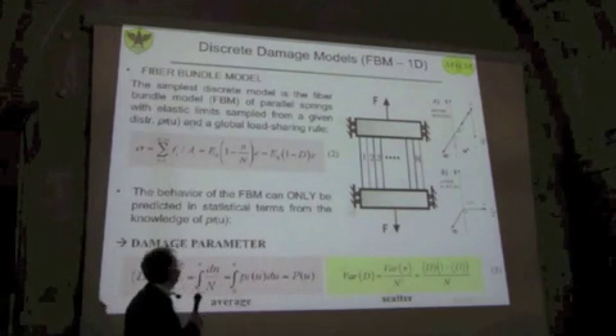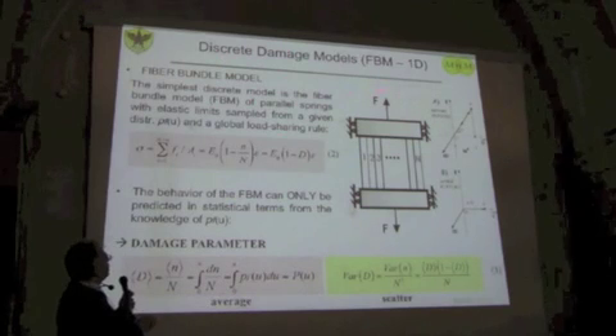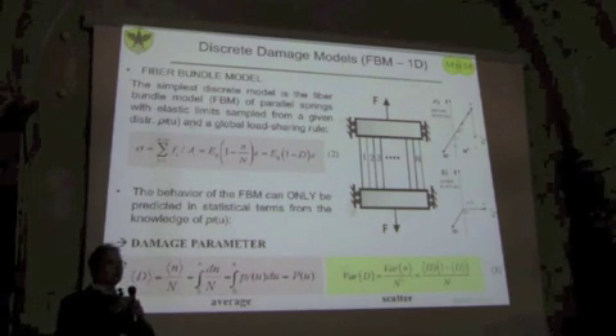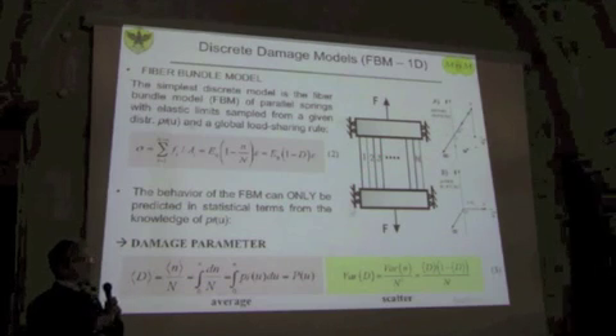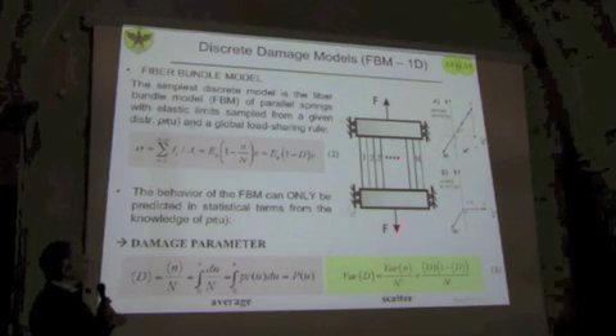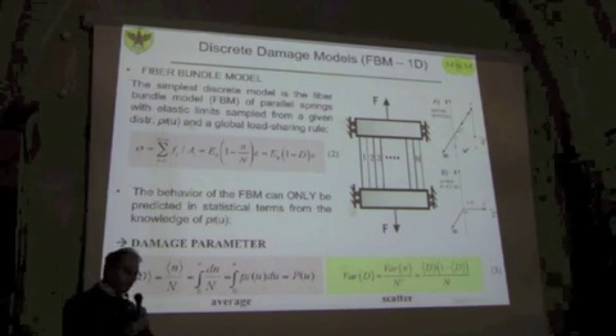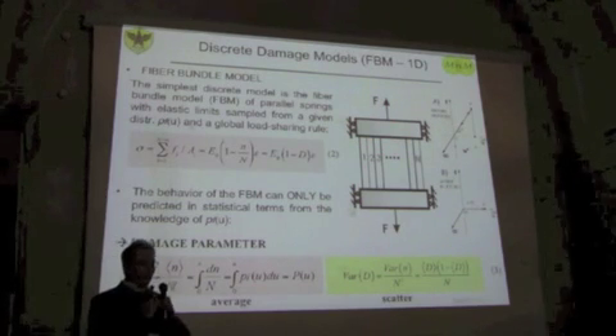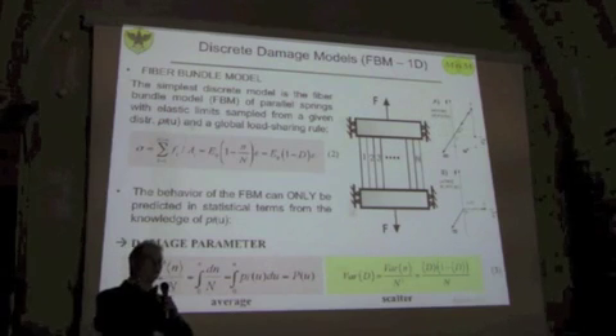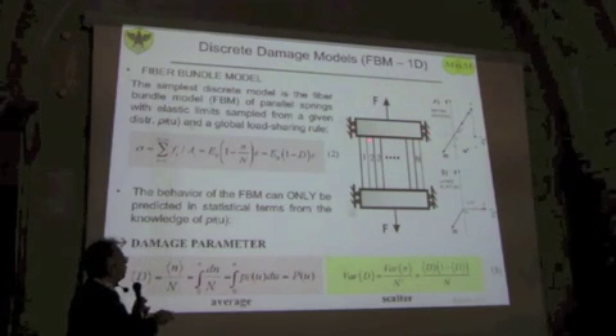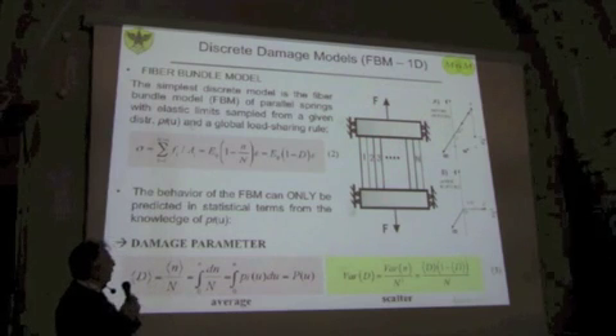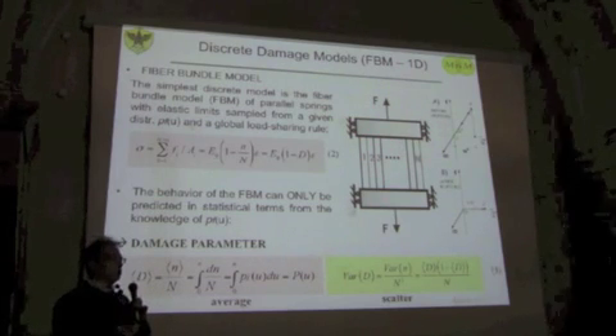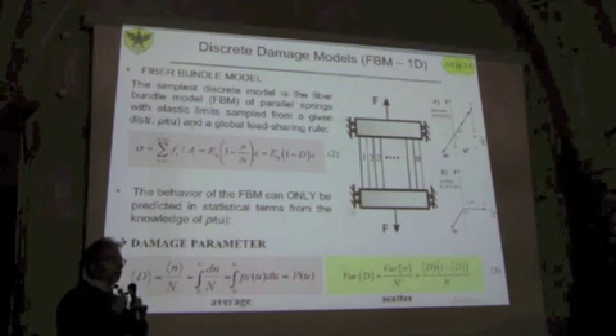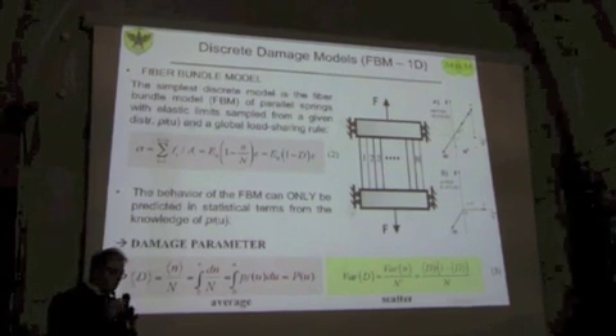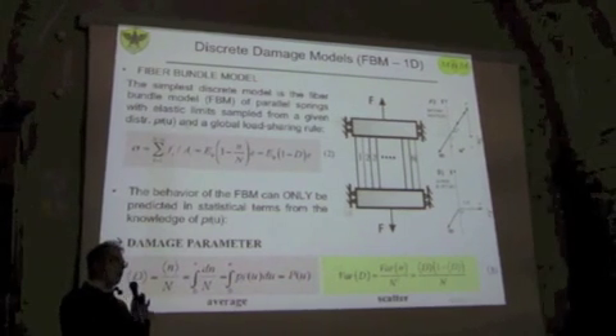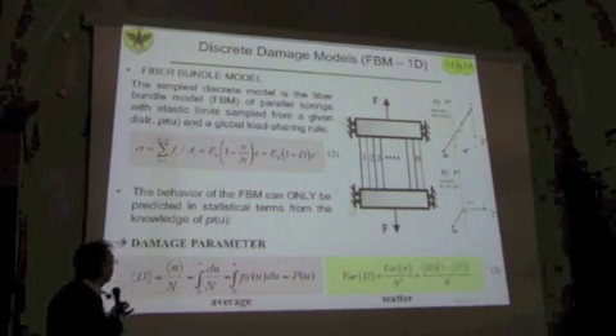I don't need to go back and forth. The simplest damage model is the fiber bundle model. Probably most of you have seen this. It's a little bit more than an exercise, but it's an excellent starting point, because for this type of system, where you have N bars which are elastic, with some microconstitutive law, and all connected together with a rigid bar, you can come up with closed-form analytical solutions. This is relevant so that you can get a clear picture of some of the things that happen at the micro scale and then reflect on the macro scale.